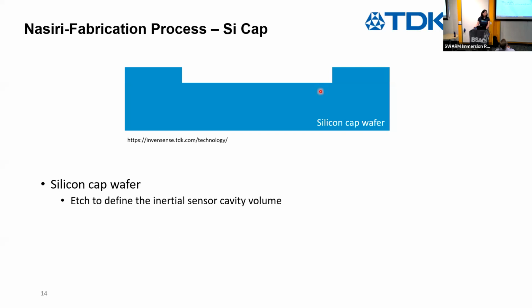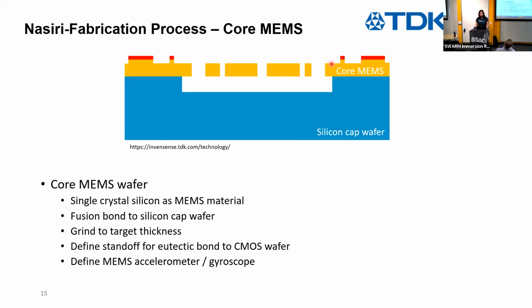I'm going to break down the Nasiri process wafer by wafer, starting with the cap wafer. This is very straightforward. You just etch a cavity into the cap wafer, and that defines your inertial sensor's cavity volume. And then in the next step, we do fusion bonding of a single crystal silicon wafer onto the silicon cap wafer. After bonding, we polish the silicon structure wafer down to the target thickness. So it's grinding and polishing and CMP.